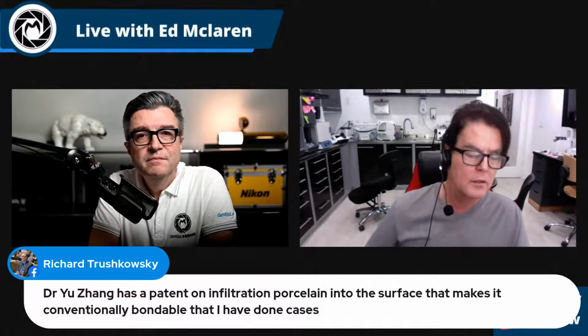One of the things I'd be concerned about, though, would be did that create some film thickness that potentially affected seating? If we're putting something on the inside of the restoration, it takes volume and takes space. The porcelain would probably need to be roughly 100 microns or more thick, so that when you effectively etched it, there was something to grab a hold of. Yeah, but you see, there are a lot of ideas, a lot of strategies to find a way around some issues we still encounter when using zirconia on an everyday basis.